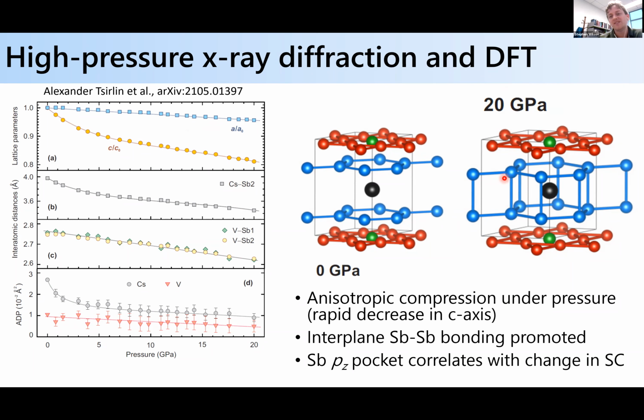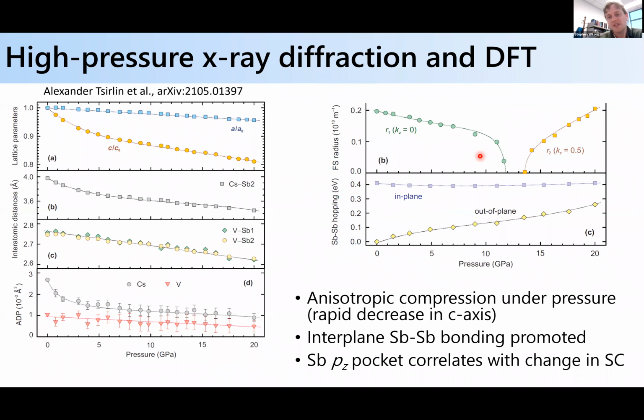By refining the structure under pressure, what they find is that as you reach this 20 GPa phase, the antimony sites get much closer together, and you start to have strong antimony hopping in this direction in their DFT models. The other effect they see, looking at the Fermi surface of their DFT models, is that as you transition potentially from one superconducting state to the other, there's an antimony-derived PZ pocket that comes and goes, vanishing around the crossover where superconductivity is purported to completely vanish under high pressure, and then it reemerges in the second superconducting regime, the SC2 regime.